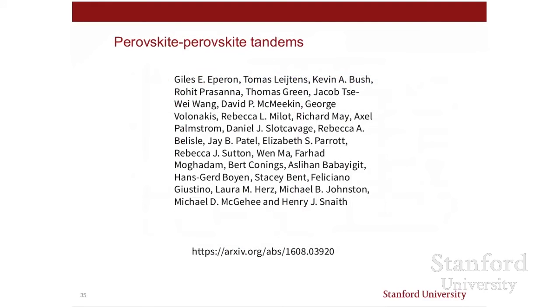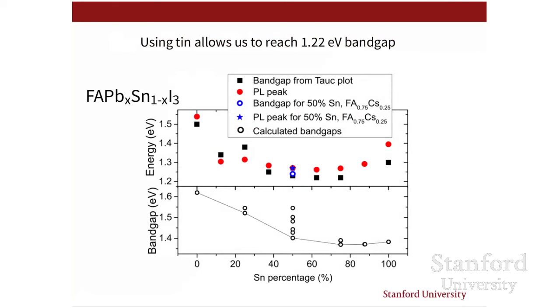Finally, I want to tell you about something that's not published yet in a peer-reviewed journal. In collaboration with Henry Snaith's group from Oxford, we've figured out how to make a low band gap perovskite and make all-perovskite tandems. This is on the arXiv right now as the paper is going through peer review. Here we're adjusting the ratio of lead to tin in the compound. And if the tin composition is around 50%, we can get the band gap down to 1.2 electron volts. That's not perfect for a two-terminal tandem, but it's getting very close to being the perfect band gap.